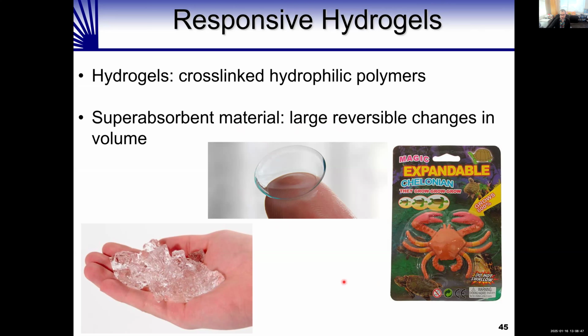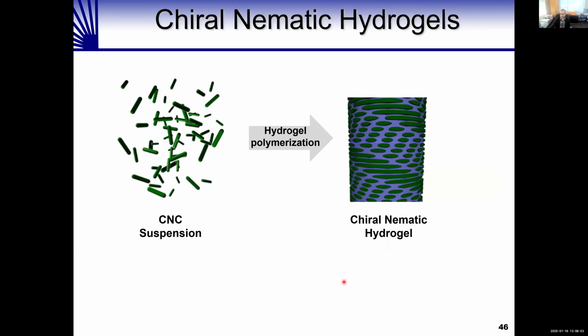So we wanted to make a hydrogel that had this chiral-nematic organization and could be colored. What we imagined doing was taking cellulose nanocrystal suspension and adding chemicals to it so that we could polymerize and form a hydrogel around the chiral-nematic organization of the cellulose nanocrystals.